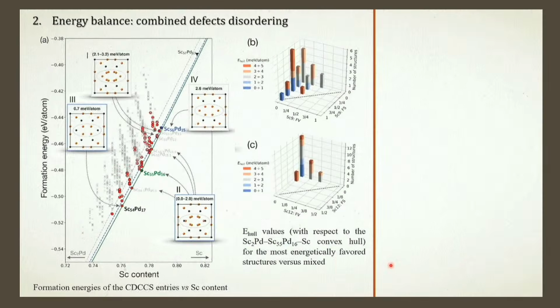So, if I take some structures from this area, for the scandium-9 position, it was confirmed that the defect introduction is really energetically favorable, but the scandium-12 position is not so favorable, so we can neglect this scenario.